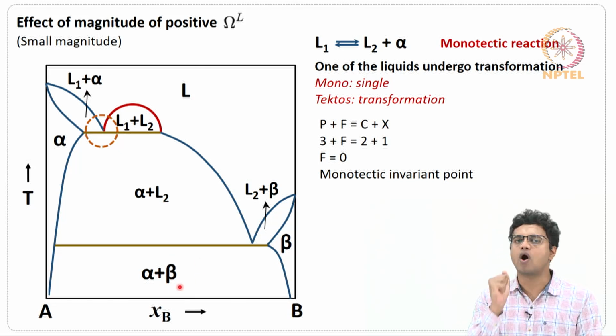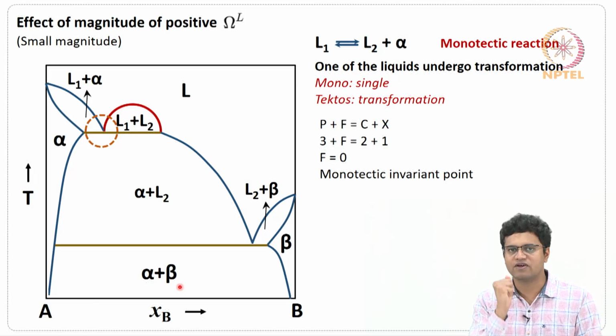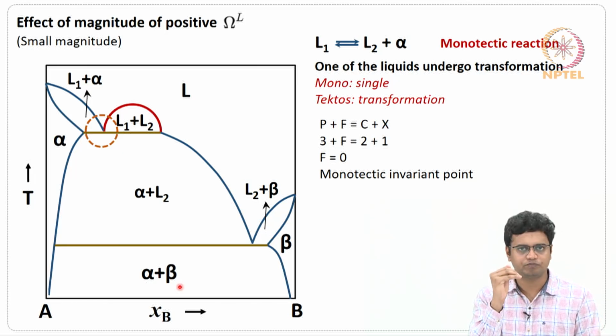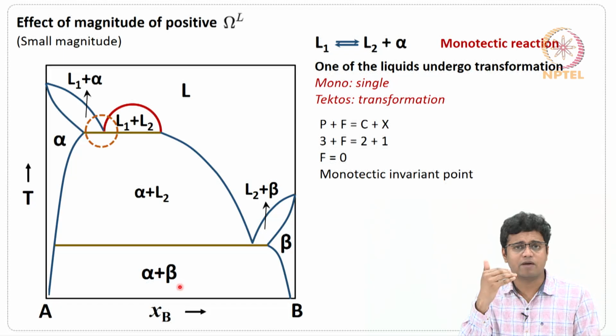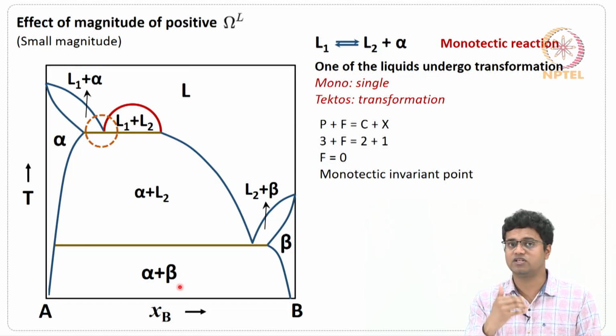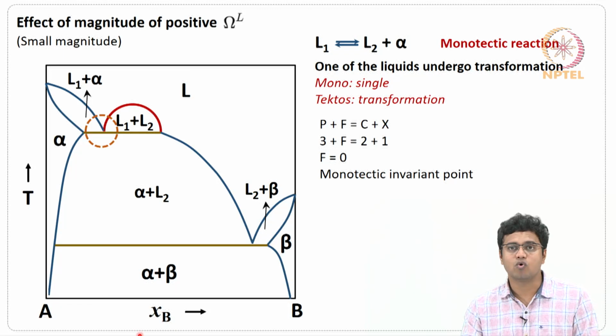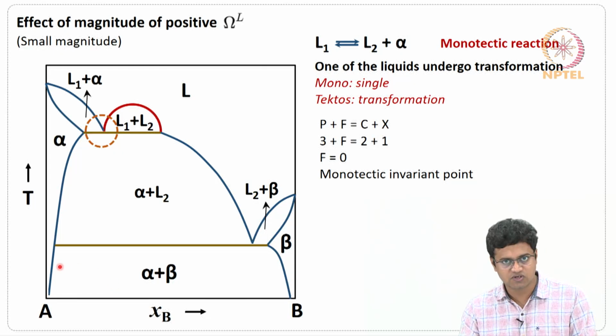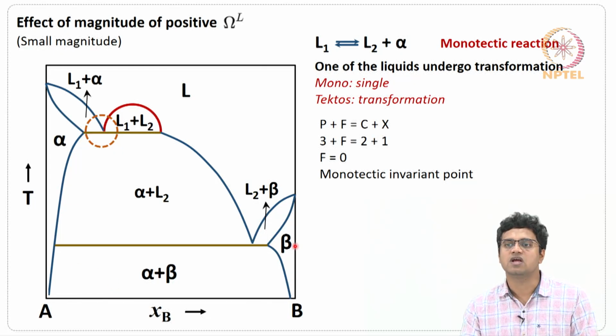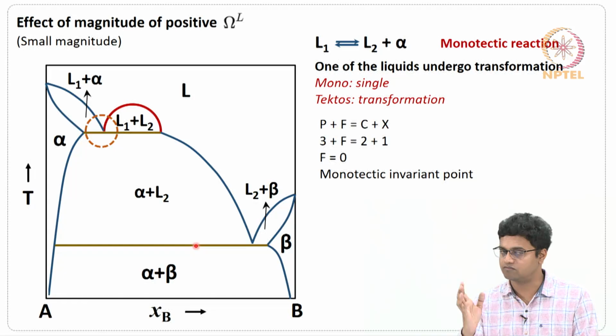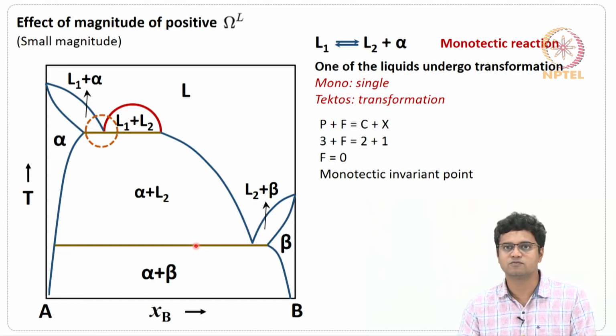So three things. One is the liquid phase separation happens at a higher temperature due to the interaction parameter being positive in the liquid state. In addition to that, at low temperature the phase separation persists. That's the reason we don't see the terminal solid solutions. However, I have shown you here the most general case. But in real systems, you do not see the terminal solid solutions.